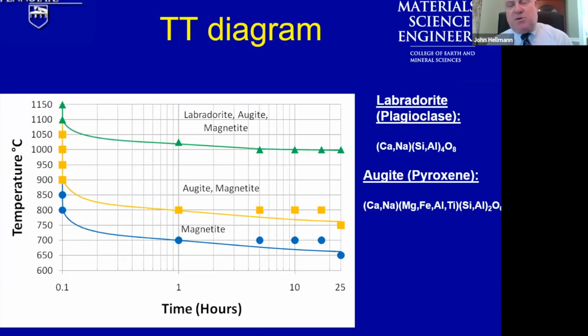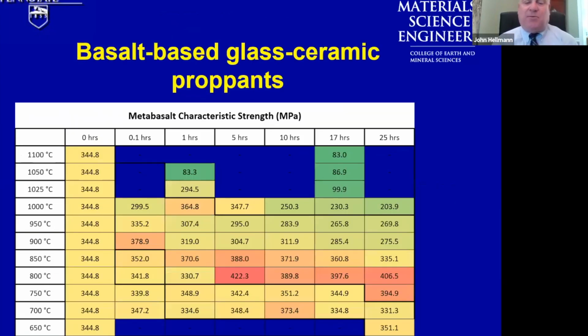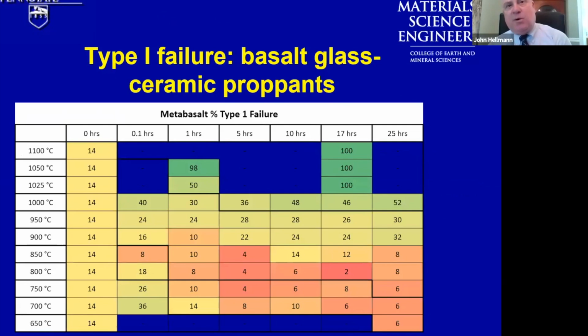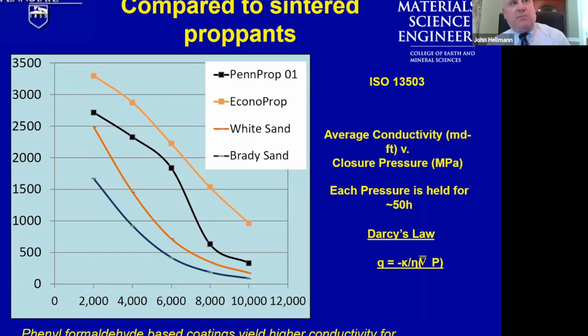We extended this work to metabasalts because that particular mining operation was closer to us and closer to the Utica and the Marcellus shales. We did the same result, or found the same result on time temperature transformation. And we were able then to map out regions of time and temperature, which would yield high strength and at the same time, low type 1 failure. So we patented this technology and we spun it out for commercialization in a startup company because we felt the material properties would be sufficient for widespread application in the propping industry.